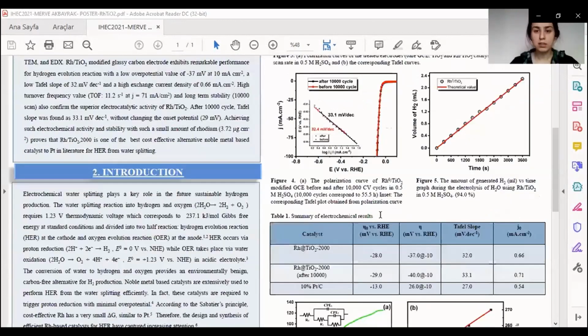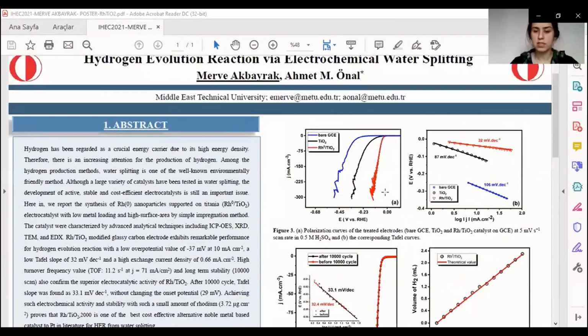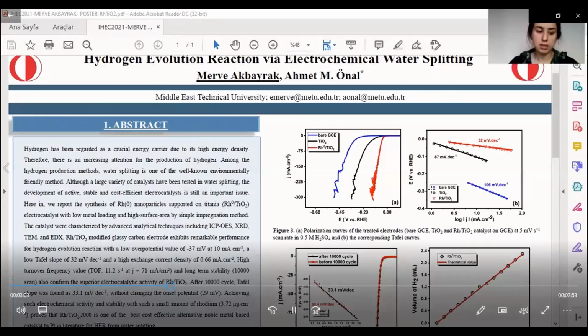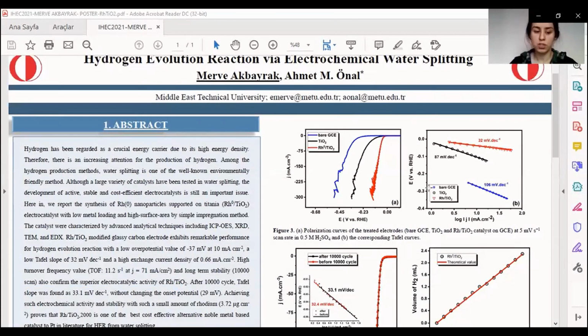The electrocatalytic activity of the rhodium titania modified glassy carbon electrode was investigated by recording polarization curves in 0.5 molar sulfuric acid solution. Since the electrocatalytic activity of the modified electrode was found to be improved gradually after potential cycling between minus 0.5 and 0.5 volt versus silver chloride, the rhodium titania modified glassy carbon electrode was subjected to potential cycling until no more change was noted in the onset potential. This point was reached after 2000 cycles of cyclic voltammetry treatment in 0.5 molar sulfuric acid solution. To check if glassy carbon electrode or bare titania without rhodium show any activity in hydrogen evolution reaction,